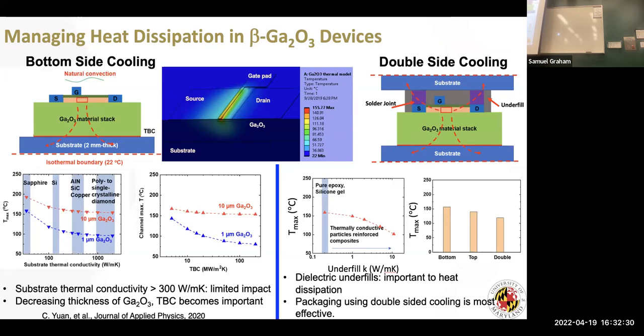The other thing that you can see is that this is the substrate thermal conductivity. So it really doesn't matter if I go to 1,000 watts per meter K. You're really not going to get much more of a benefit than if I'm back here at something like silicon carbide.